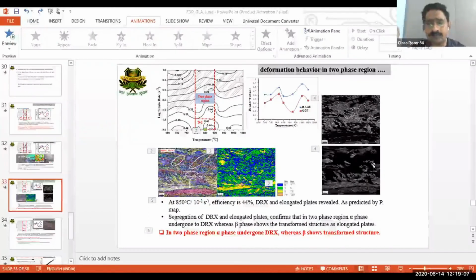So a lot of literature is available that if you are having the peak point and then the flow curve, after strain hardening, is decreasing, or flow softening is there, we normally use that as an indication that DRX may happen in the deformed microstructure. But along with this softening, along with this DRX, sometimes some kind of instability may also exist. So for this, you can see some published papers.